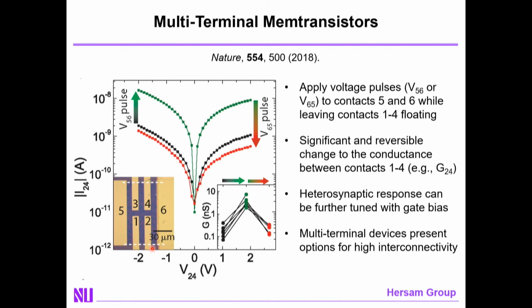This is indeed the case. What I'm plotting here is the current voltage response between contacts 2 and 4 as a function of voltage pulses between contacts 5 and 6. And you see very clear non-volatile tuning of the orthogonal conductivity as a function of voltage pulses.